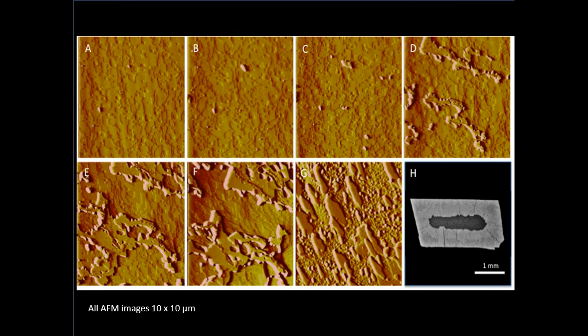And the number G is after a day where the nanoparticles have merged, so it's a different orientation here because I took it out and put it back in. The nanoparticles have merged and we're getting straight edges. We're getting the formation of a new crystalline phase on the surface.